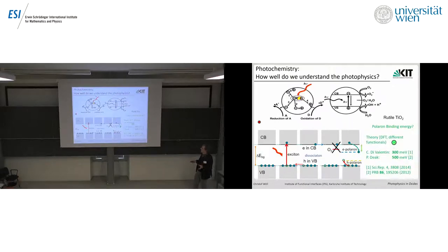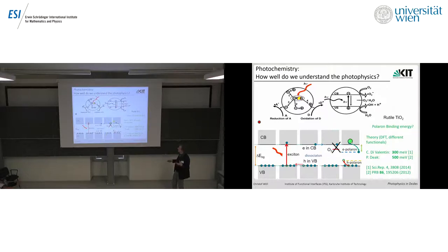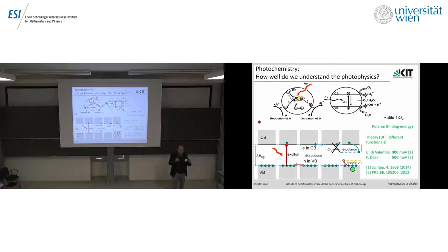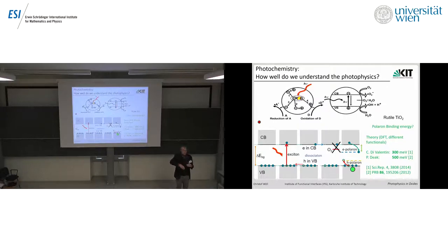In titania, the binding energies are certainly substantial with regard to the band gap, so you need to consider them. Drawing pictures without this is simply not correct. The full photophysics will need to look into these polarons. There are very nice time-resolved experiments with very high time resolution on exciton formation, but if we want to do photochemistry, we have to look at longer timescales — we have to transport the excitation from the bulk to the surface — and so we should look at polarons.